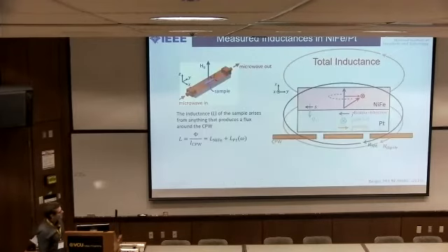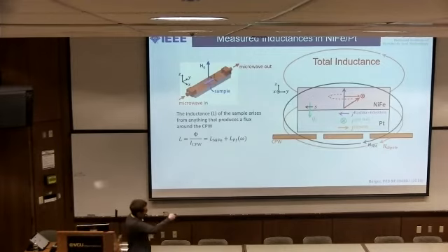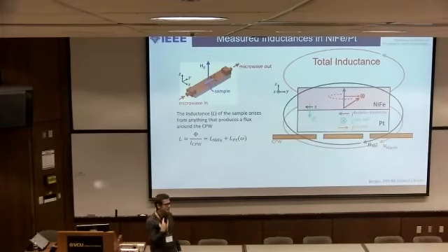Okay, so now let's replace the copper with platinum. This has a high spin orbit coupling, so we should expect spin orbit torques, or the inverse of that actually in this case. So now again, we go into ferromagnetic resonance with our nickel iron layer, and because of spin pumping, we're going to generate a pure spin current going into the platinum layer shown here. Then that pure spin current, through the spin orbit torques, will be converted to a charge current.